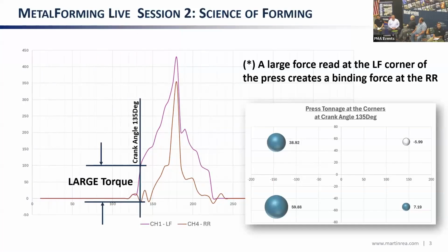One of the visuals that you can take out of this data, looking at the left front corner and the right rear corner, you can isolate those two curves, and you can see that it creates a very large torque on the press.